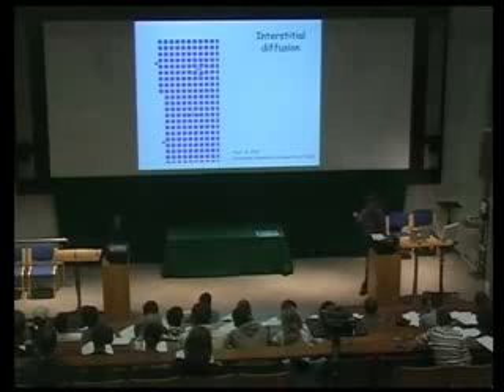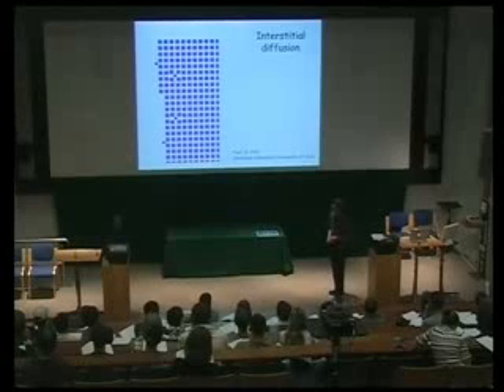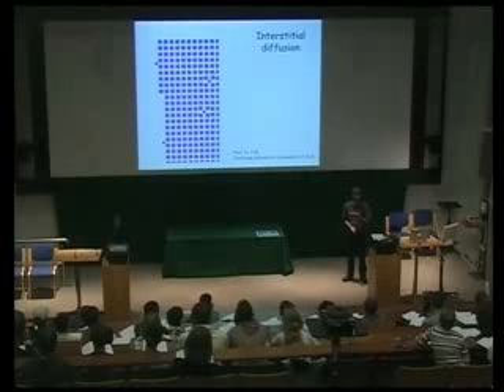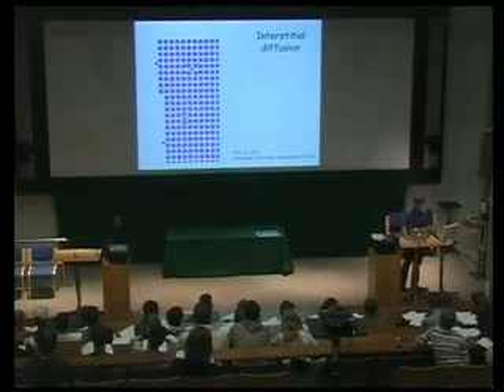And this is interstitial diffusion. Interstitials generally fit very badly inside the holes in the crystal, so the distortions involved are somewhat larger. But there's a huge number of interstices available in the lattice, whereas there are very, very few vacancies available in a usual crystalline lattice. So interstitial diffusion tends to be faster.